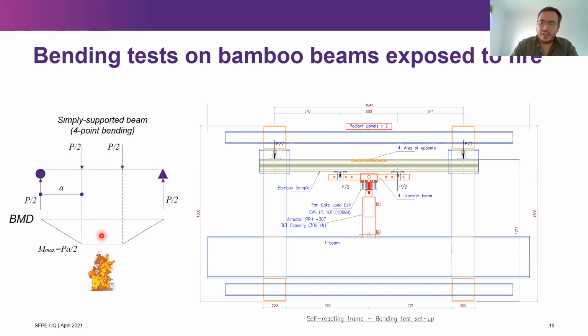We obviously couldn't carry out those experiments at the structures lab because of the release of smoke and because of the elevated temperatures during the test. Obviously, we were also creating some risk for the equipment. So we designed our own testing setup, and that was one of the biggest tasks of my PhD, designing this setup. So basically what we did is we turned this upside down. So instead of applying the loads downwards, we applied the loads upwards, right?